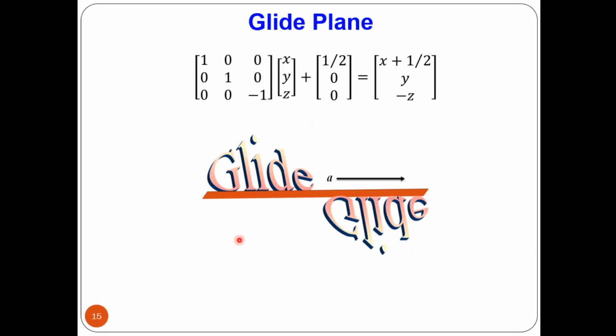This is a symmetry operation that is described with the help of two parts: translation and reflection. So in here, as you know, reflection has taken place along the z-axis because we see the z coordinate with changed sign, and then the translation has taken place along the x-axis, and half means half of the lattice parameter, which is a in here. If we have a, the magnitude of the lattice parameter, then the magnitude of the translation is half a.